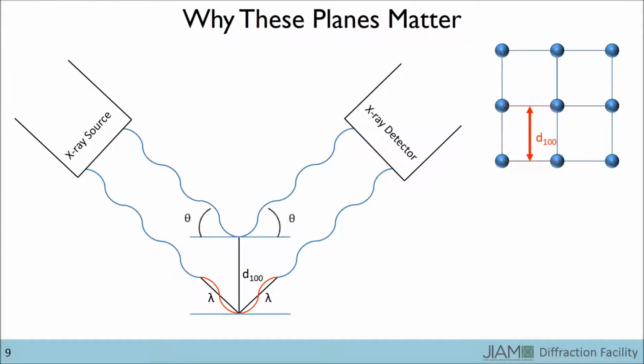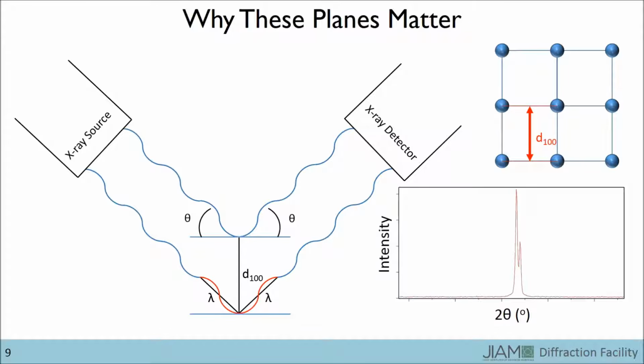The angles at which the X-rays strike the sample and are diffracted are designated by theta in the so-called powder diffraction configuration. If the X-rays from the top path reach the detector at the same point along the wavelength as the X-rays from the bottom path, constructive interference occurs and a peak is produced when the intensity is plotted as a function of 2 theta. If the X-rays reach the detector at different points along the wavelength, destructive interference occurs and all we get is background.